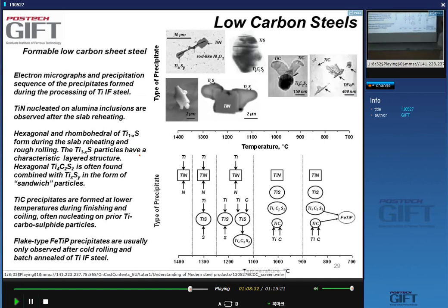Well, it's related to the fact that in austenite, the solubility of carbon is very high, right? Remember, that was one of the big differences between ferrite and austenite, this carbon solubility. So forming carbides in austenite is much harder than forming carbides in ferrite because carbon is very soluble in austenite. So we usually have to wait till we have ferrite to precipitate carbides.